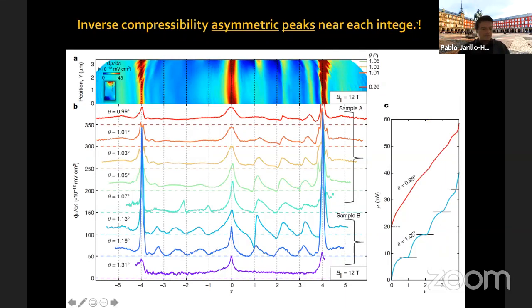Now, I have only a couple of slides left. Let me just tell you what we measure. As we go through the different twist angles, what we see are these traces of inverse compressibility. I want you to focus on the fact that for 1.31 degrees, this is almost featureless, except for the band insulator gaps and the charge neutrality point. For 0.99 degrees, also only weak features. But in between, in this magic angle range, take for example this trace at 1.13 or 1.07 degrees, you see the sawtooth behavior in the inverse electronic compressibility.